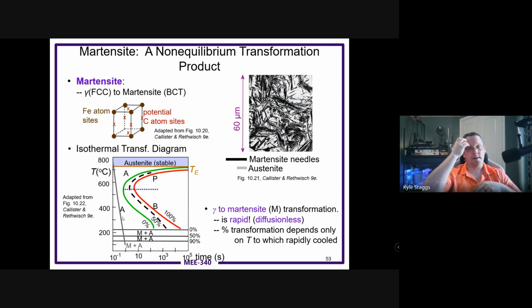And this is why they use something like oil to do it, so they very quickly get down into the martensite region. But if you take even 3 or 4 seconds to get below those temperatures, so if you pick it up out of the oven and it's cooling off and cooling off, and then you quench it suddenly, you're going to fall through the pearlite and bainite regions. And so you'll have a little bit of hardness, but it's not going to be as hard as it would be otherwise. And so you guys are doing the Jominy end quench test in lab. You're going to see the end being much, much higher in hardness compared to the material that takes longer and longer, because of how it's passing through this curve. So this is where some of those principles come from.